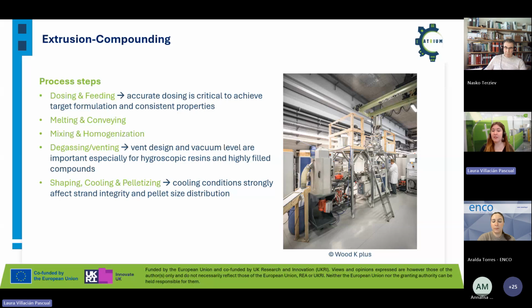By adding this screw that is all the time mixing the material, we have these homogenized blends. For some of the materials, for example, for hygroscopic resins and also for highly filled compounds, it's also important the degassing and the venting because we do not want to have high pressures within the extruder. As I commented already, we have also the cooling and the pelletizing. The cooling conditions also strongly affect the pellet integrity and the pellet size distribution, so it's really important also to control it.